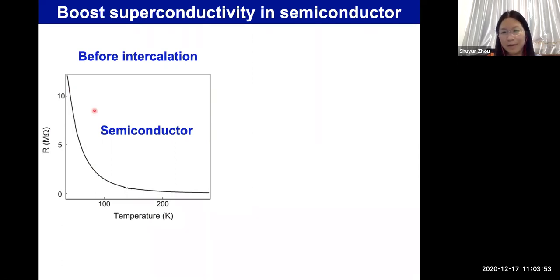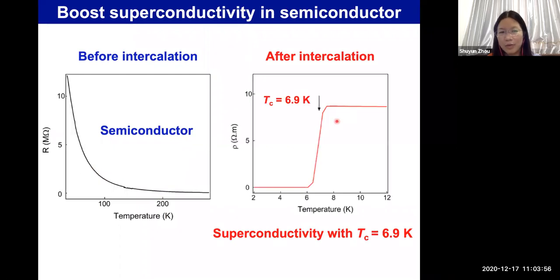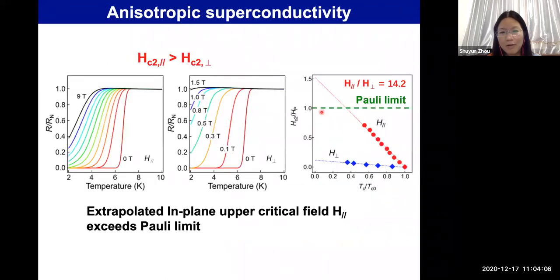Now, after intercalation, we see that there's a transition to zero resistivity with a transition temperature of 6.9 Kelvin. And also, the superconductivity shows a very anisotropic response to applied magnetic field. Here, this upper critical field does not go beyond the Pauli limit in our measured temperature range. However, if we extrapolate this line, it seems to suggest that this upper critical field may go beyond the Pauli limit if the temperature is low enough.